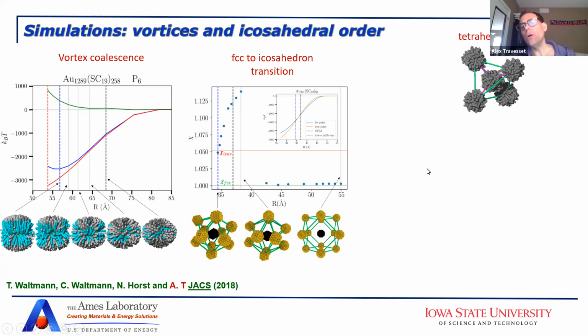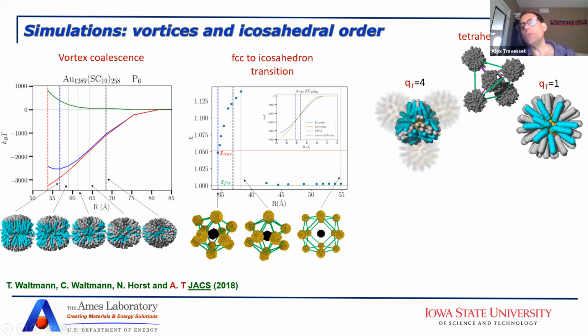And here I would like to show you what happens if you have a tetrahedral. So here you have a central nanoparticle surrounded by 4 nearest neighbors. And then you start approaching these nanoparticles together. And then what you see is that at the situation where they are at the minimum of the free energy, you see that the particle at the center has this configuration, which is 1 vortex, 2 vortex, 3 vortices, and 1 vortex behind. So they form the 4 vortices that we expect. And the particles that are actually in contact, they have just 1 vortex because that's the one they are here. So here what we show is with an all atom molecular dynamic simulation, the presence of all these vortices.